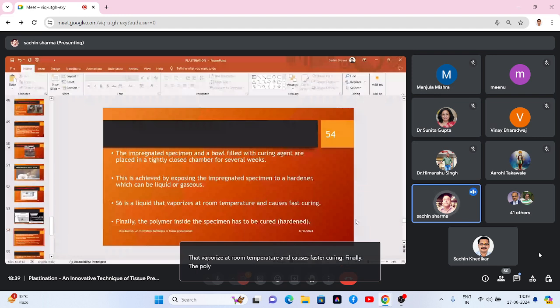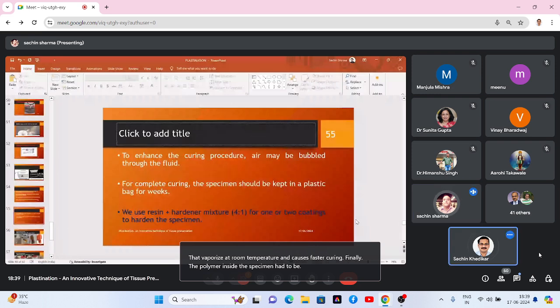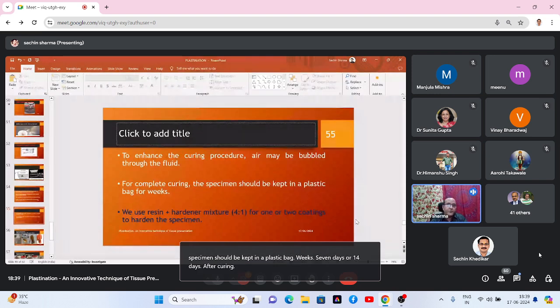Finally, the polymer inside the specimen has to be cured. For complete curing, the specimen should be kept in a plastic bag for weeks, 7 days or 14 days after curing. Before curing, if you place it in the bag, it will attach to the bag and your specimen will be destroyed. So after curing, you will keep it in a bag for some time. We are performing with epoxy resin, so we are using the mixture of resin and hardener in a 4:1 ratio. After impregnation, we will apply a coat on the specimen, one coat and two coats, so that we will get a harder specimen.